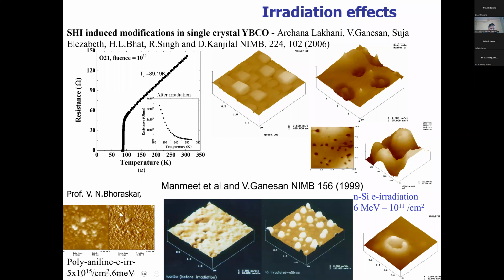And this is simple polyaniline. If you irradiate with very high energy, you can see what will happen to the polymers. You break them, hydrogen will evolve, nitrogen also will go away, only carbon is left over. Carbon at high temperature and high pressure, because of very high energy ions. How much energy? 6 million electron volt, or 100 million electron volt. Such a high energy is deposited in a small distance, too much energy, the temperature will go up. So at high temperature, they become diamond. That is what nano diamonds are.